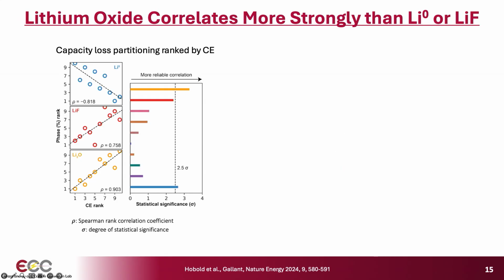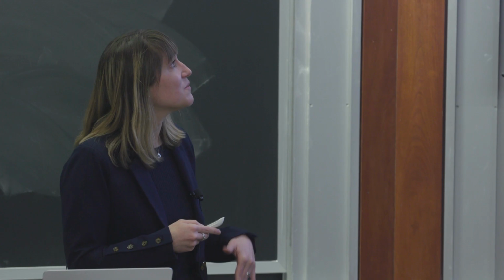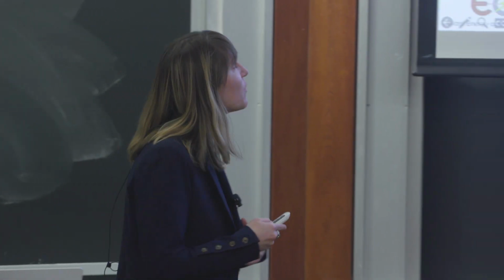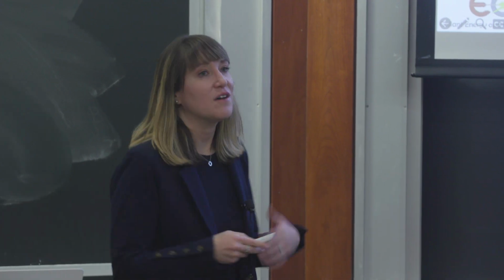So to make better sense of the trends with Coulombic efficiency, we conducted a statistical analysis, and it tells us essentially of all of the different phases which have the strongest correlation with CE. So of the SEI phases, the two that correlate most strongly are shown here. Lithium fluoride does have a positive correlation. However, the correlation with lithium oxide is actually quite substantially stronger than that with lithium fluoride. And this was, I think, surprising to many in the field. And the correlation is actually even stronger than that of the anti-correlation between dead lithium and Coulombic efficiency.